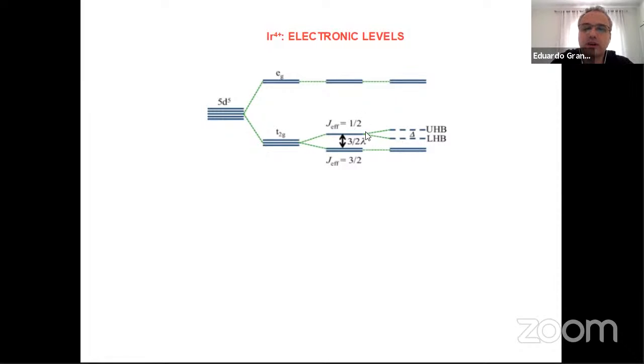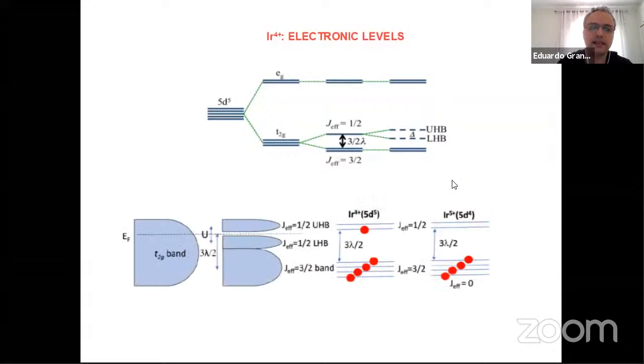That turns out to be a very sharp electronic level, and because of electron-electron correlations, it leads to a gap opening due to the Coulomb interactions between electrons. So we have actually 2 levels, which are called the lower Hubbard band, or level, and the upper Hubbard level. And that's the basics of the electronic levels of these iridium 4+ iridates.